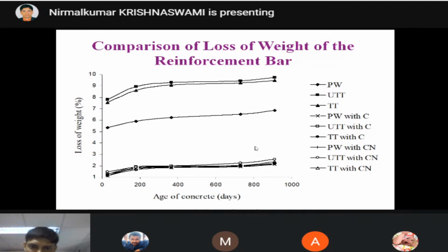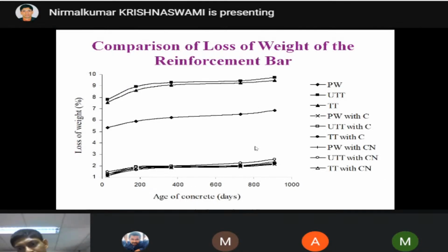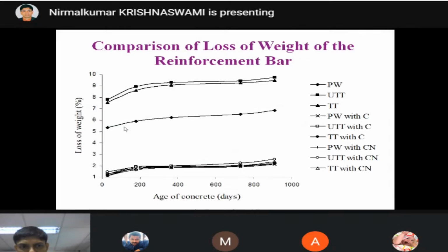We broke the cylinder, took the iron bar, and we know the previous weight. Then after 28 days we tested the weight. See the difference: without the addition of admixtures, it is around 10 percentage. Even when using potable water, since it is an induced corrosion, it is 6.2 percentage.